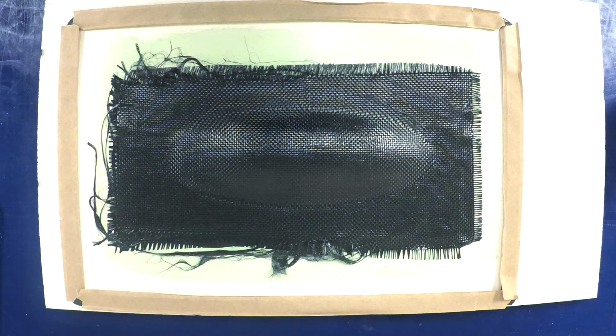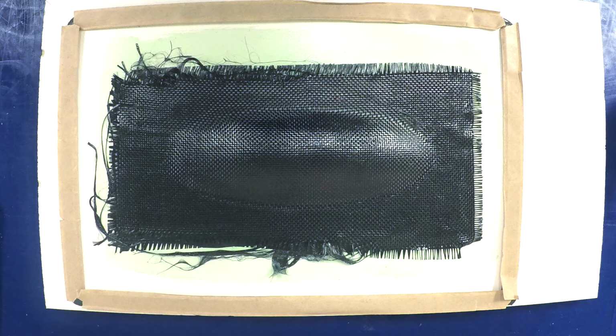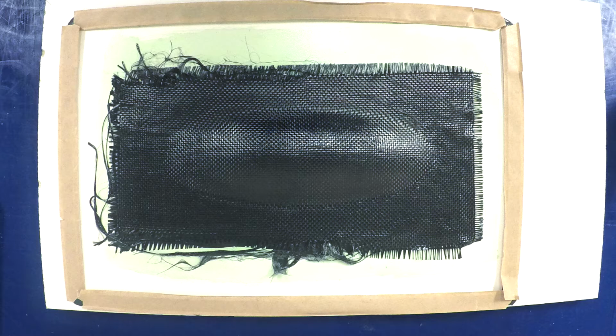While you may leave your final product to dry just the way it is now, for improved results you can always attempt to place weights or any form of pressure over it. If doing this, try and use a release film to keep whatever weight you're using from becoming stuck to the laminate by gluing itself to the epoxy.